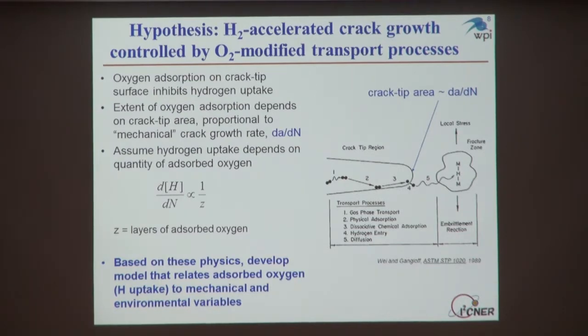So we wanted to try to develop a model to explain all the behavior that I just showed you on the two previous slides. To start off, we wanted to have some hypothesis of what physics were operating, and that's what I'm showing here on this slide. Our hypothesis, as I mentioned, is that this hydrogen accelerated crack growth is somehow controlled by oxygen modifying the hydrogen transport processes. Specifically, oxygen adsorption on the crack tip surface somehow inhibits the hydrogen uptake. I'm showing you the same schematic. This is our crack tip. Oxygen is interfering with these transport processes, most likely with the dissociative chemisorption. And the extent of the oxygen adsorption is going to depend on the crack tip area.